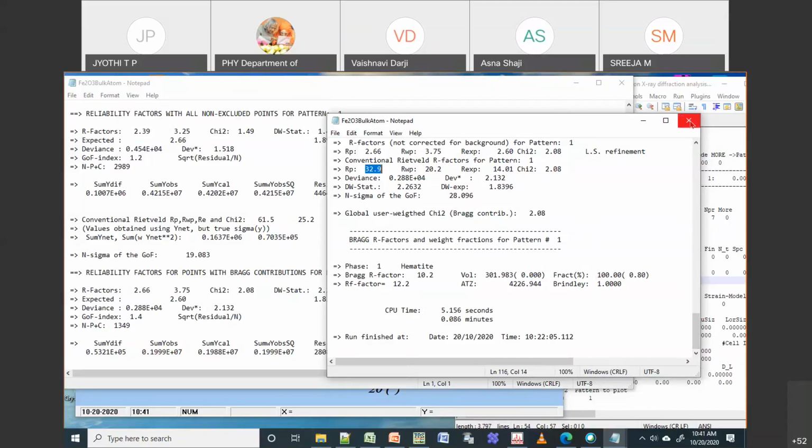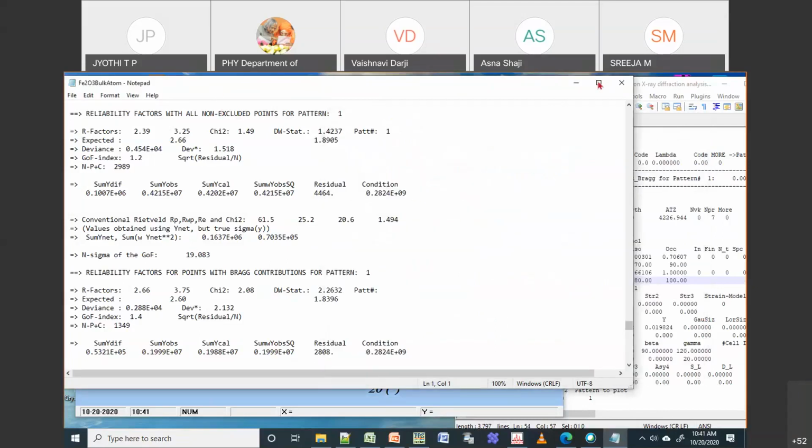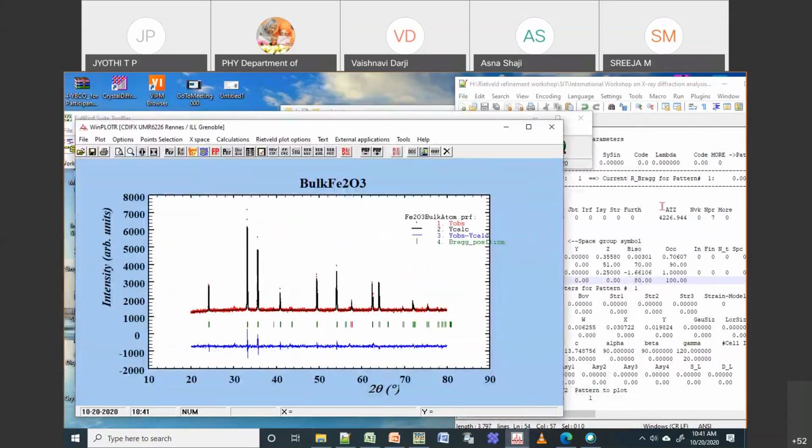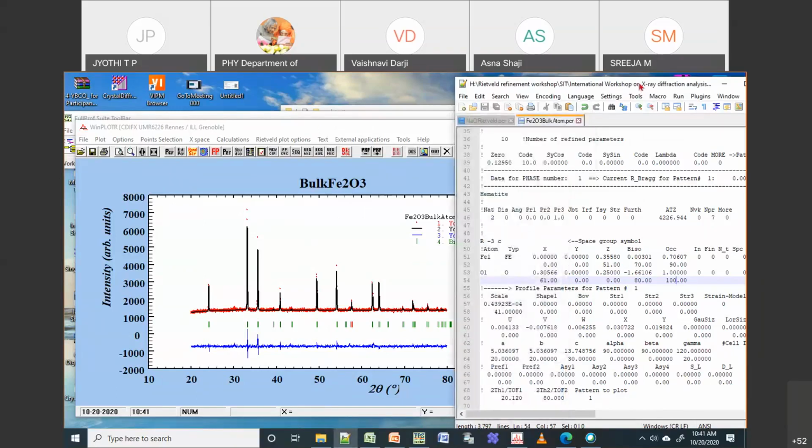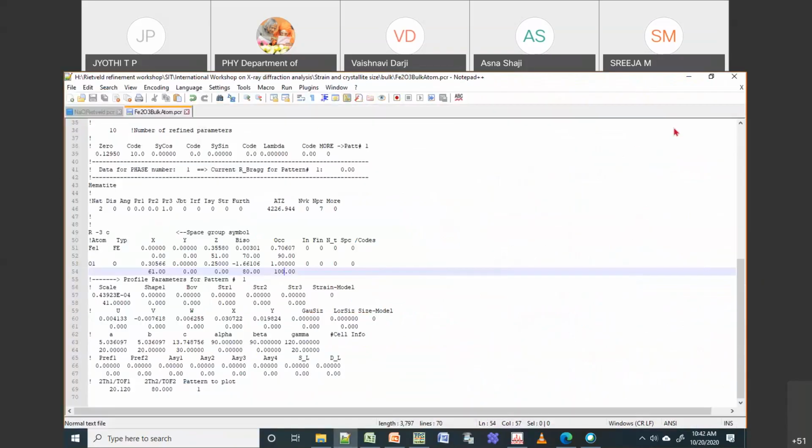Okay, so these are the values that you can get from your Rietveld refinement. So I'll check if there is any other question. Okay, since BISO is a kind of energy, can its negative be acceptable? Yes, it's acceptable, especially when it comes to oxygen and low weight atoms like oxygen and fluorine. It can actually go negative because there may be some high distortion for your oxygen.